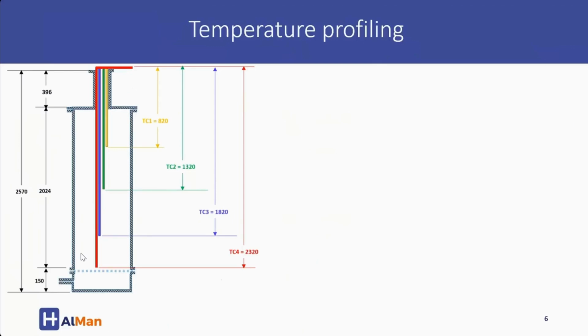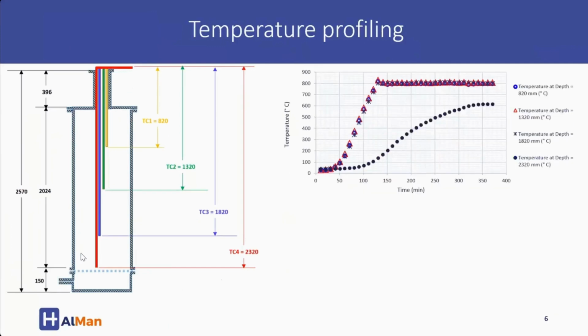Looking at the profiling of this vertical retort, we had thermocouples inserted at different heights throughout the height of the retort. The first profiling showed that the top two thermocouples reached temperature very quickly.